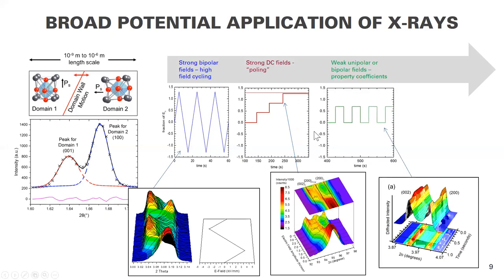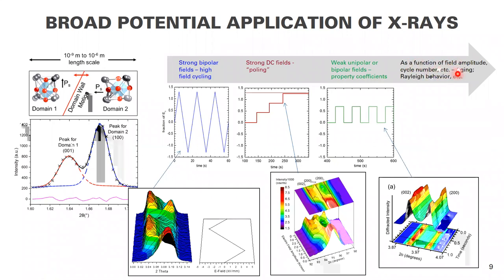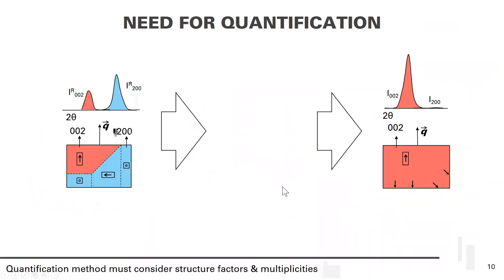You can also think about taking a poled material and then applying weak unipolar or bipolar fields, similar to what would be measured during property coefficients. Okay? And then as a function of field amplitude, cycle number, et cetera, you can study things like aging and contributions to Rayleigh behavior. So there's broad potential application of X-rays for studying these types of phenomena.